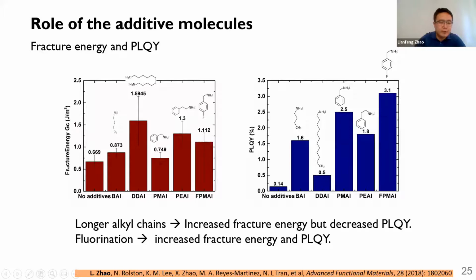We measure the fracture energy of the perovskite thin film as an indicator of how resistive the film is to cracking, and we measure the photoluminescence quantum yield as an indicator of how efficient the light emission is. When we compare the BAI, DDAI, or PMAI versus the PEAI, where we tune the alkyl chain length, you can see the fracture energy increased if we increase the additive size. But on the other hand, the photoluminescence quantum yield decreased. So in other words, if we control the alkyl chain length on the additives, we will have a trade-off between optical and mechanical property.